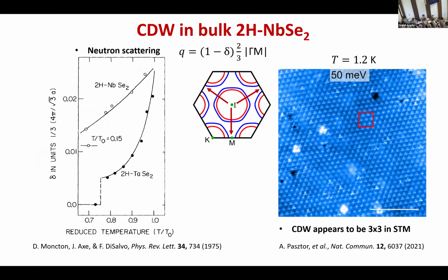For this system, it has a charge density wave, and the mechanism for the charge density wave is still under debate. The Q of this charge density wave is roughly 2/3 of the distance in the Brillouin zone from gamma to M point. However, it's not exactly 2/3. There is a very small percentage of deviation from 2/3. And from neutron scattering, people also saw this. But the exact reason for this is, I think, not really well understood.